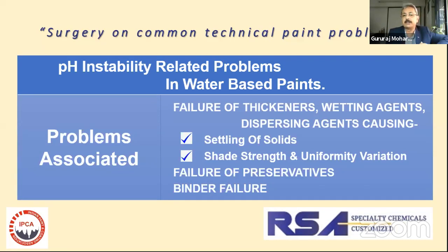Most of the additives, the thickeners, the wetting agents, the dispersing agents are pH dependent. So if your pH drops, they will stop working. And you will see complaints like the solids settle down, the shade strength is lost, the uniformity of the shade is not very good. You might see spots appearing.